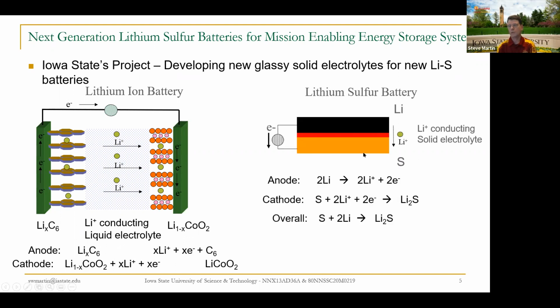And our structure will look like this: lithium metal with a very thin separator and lithium sulfide. Our reaction is 2 lithium to release 2 electrons. That goes in the external circuit. Those 2 electrons then reduce the sulfur to form lithium sulfide.